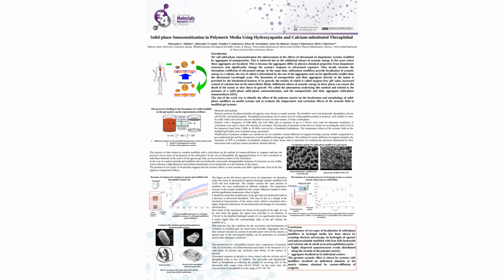To conclude, 2 types of localization of solid phase modifiers were demonstrated in hydrogel media using scanning electron microscopy. The first type consists of highly dispersed nanostructures distributed relatively uniformly along the strands of the polymer matrix. The second consists of aggregates localized at individual centers within the matrix.